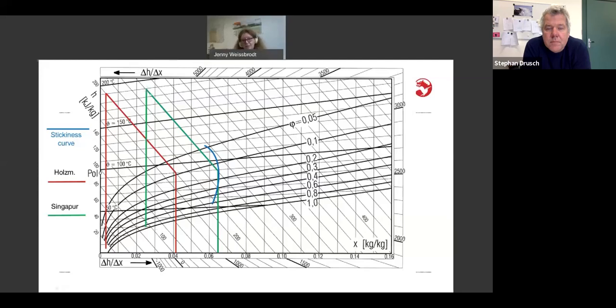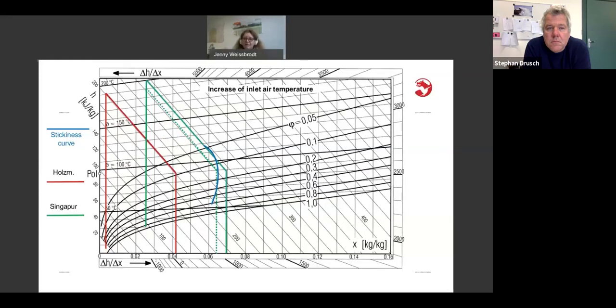Now I start my drying experiment. In Singapore, the water will evaporate, the drying air takes it up, and it touches the stickiness curve. So for the same drying experiment under the same conditions, in Holzminden we will get out a nice free-flowing powder, and in Singapore it will not come out, it will stick to the walls of the drying chamber. So what is a normal reaction any operator will have? It doesn't dry. I will increase the inlet air temperature.